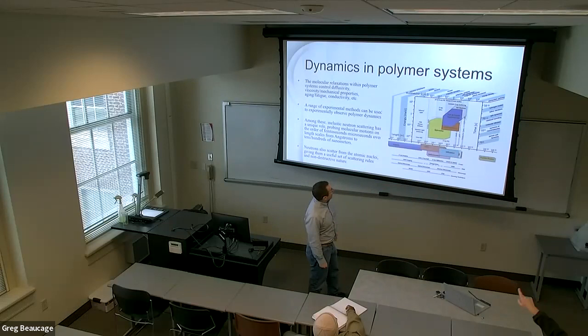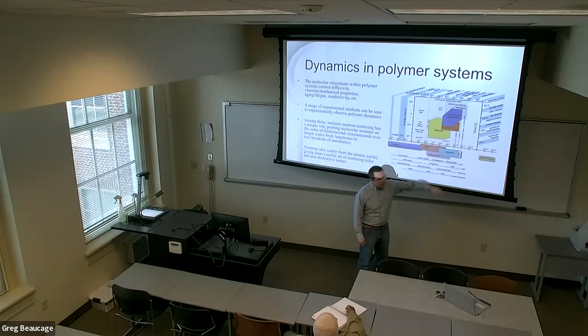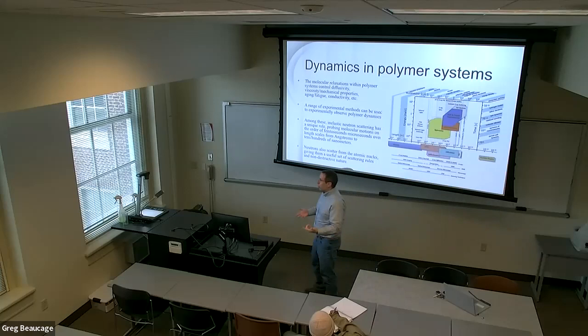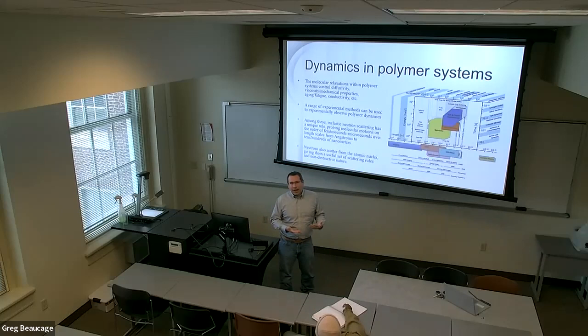Yeah, so the idea he's getting to here is that when you're doing a scattering process, the wavelength of the incident radiation is important. It actually determines the time and length scale that you're probing. When you get a scattering event, the wavelength of light is hundreds of nanometers, which gives you a limiting resolution to your scattering process. If you use thermal or cold neutrons, the wavelength of those particles is on the order of half a nanometer, so you can really tighten that up and increase the resolution of the scattering process.